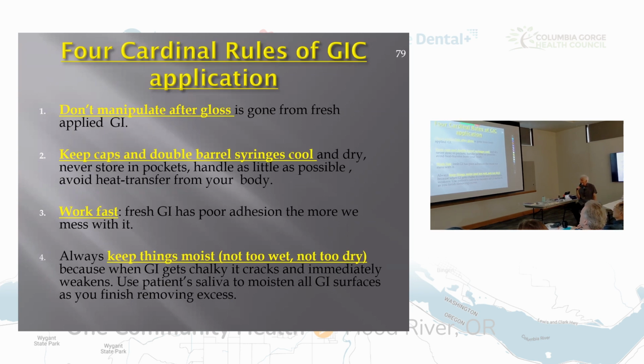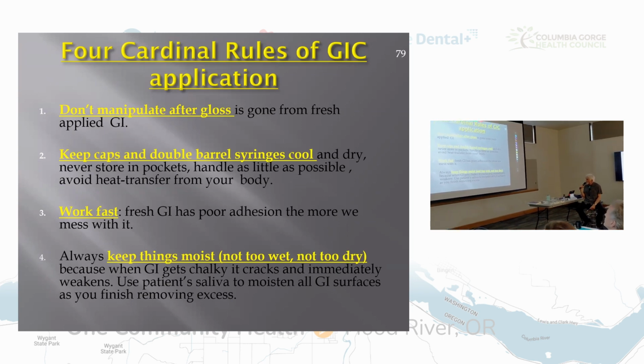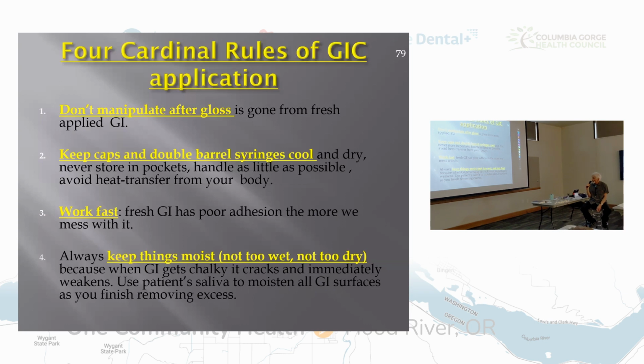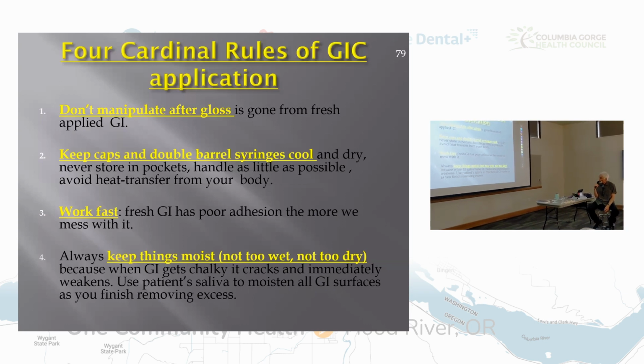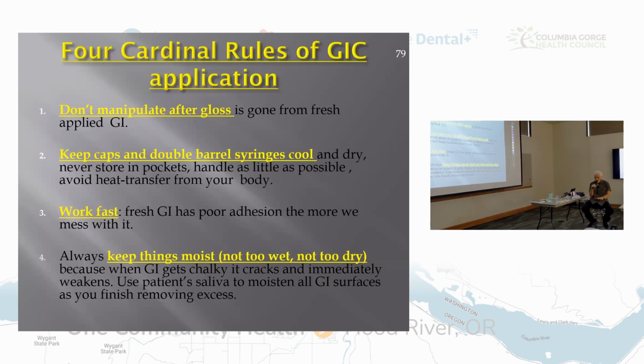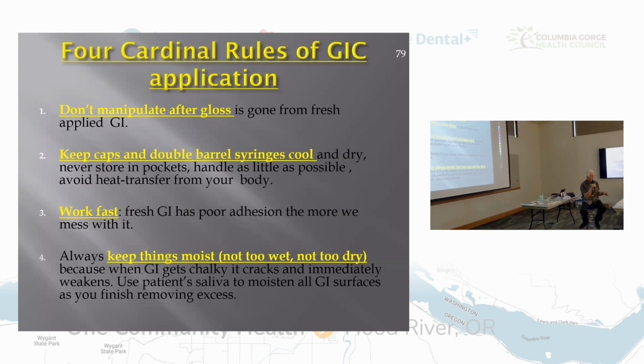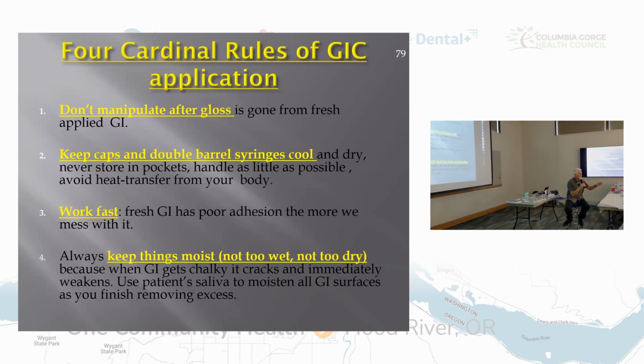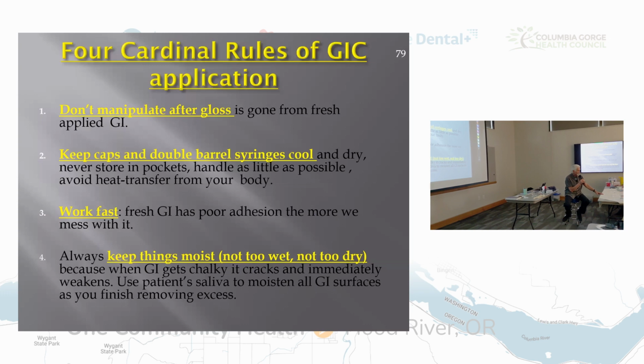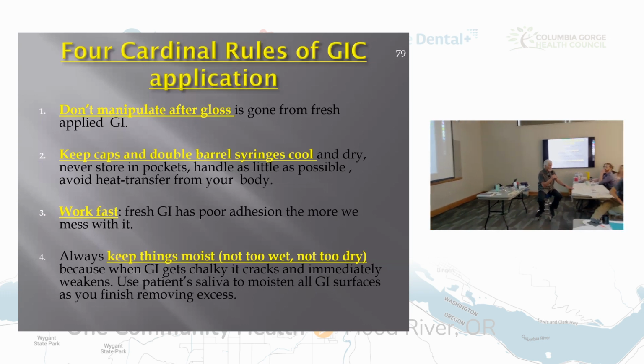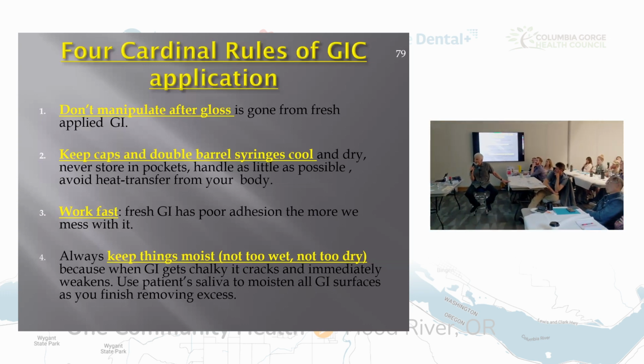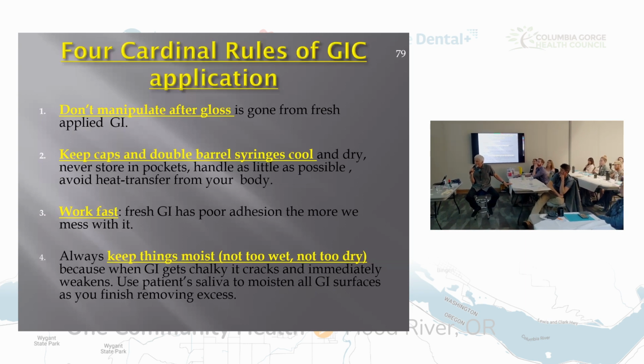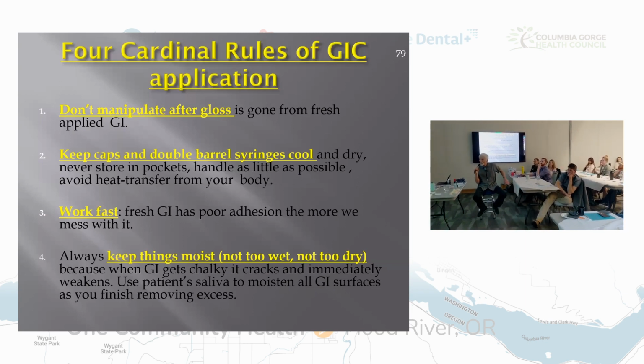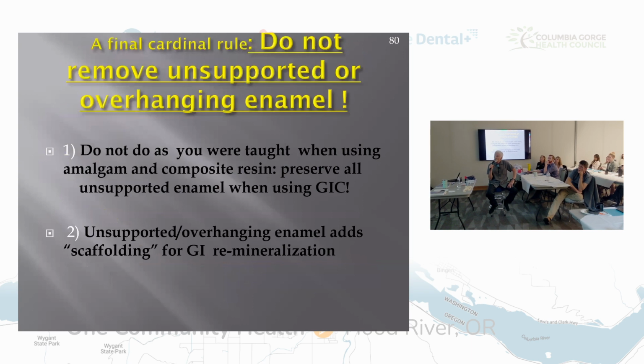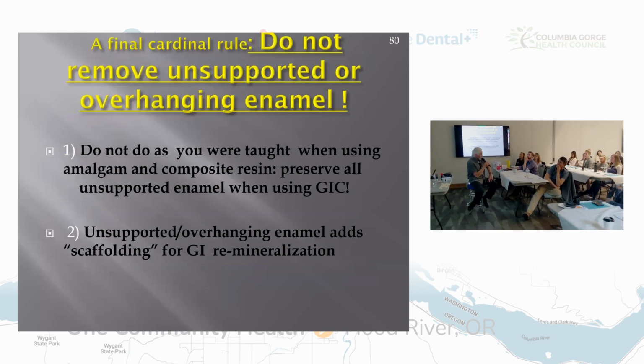That's the critical thing. Always keep things moist, not too wet, not too dry, because when glass ionomer gets chalky, it cracks, and it immediately weakens. That's the kiss of death. Take it out. If it starts cracking and getting chalky, you just screwed up. Start all over again. Just pick it out of there with a spoon excavator. Doesn't matter. Just get it out of there. Use the patient's saliva to moisten all surfaces as you remove excess.